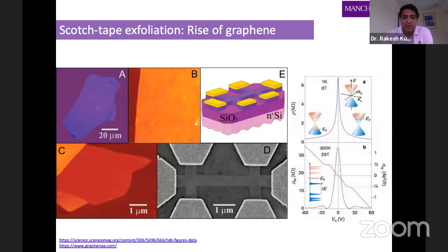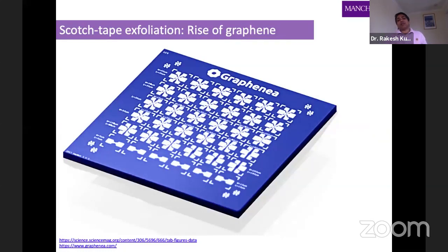For example, what you see in picture A is a flake of graphene. It's a micron size flake. And picture B is just an AFM image of the same flake. But you can make devices, for example, in figure E, you would find a Hall bar made on a graphene flake. The graphene was patterned in order to make a Hall bar. So that was the first experimental device that the group of Professor Geim and Professor Novoselov studied for extracting all the electronic properties of graphene. In 2004, we could only make a graphene flake, but over time, there is a need for large scale fabrication of graphene in order to make electronic devices.